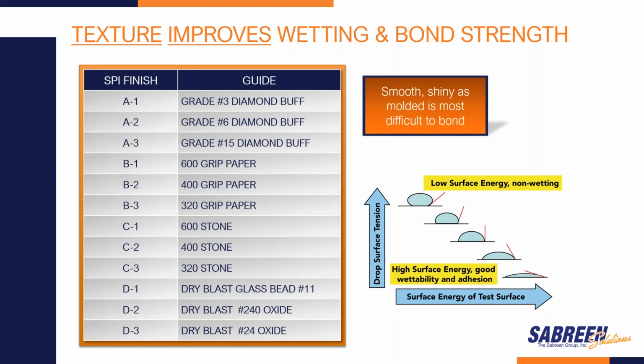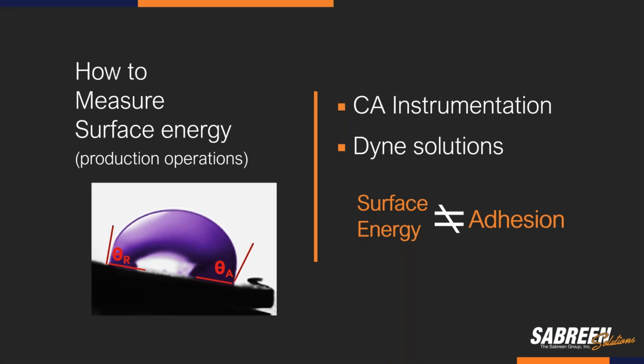Now, a very important part to understand is that texture will improve wetting and bond strength. When you have a part that's smooth, shiny, as molded, that's going to be the most difficult to bond, and many of our parts used in industry are like that. So keep in mind, whenever you can slightly modify that to a B1, a B2, or a C1 type finish, that will significantly enhance the wettability and the bond strength, because it's going to allow for mechanical bonding. A lot of emphasis is placed on contact angle and surface energy, but it's important to understand that surface energy does not mean you're going to have strong adhesion.